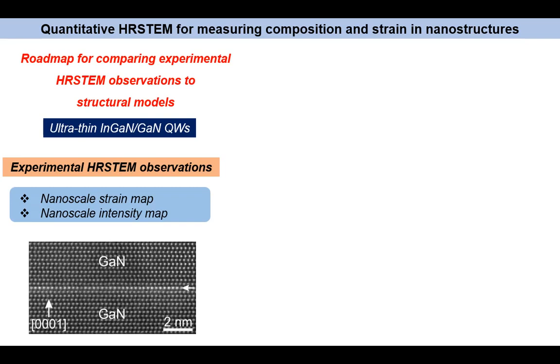So now let me go into more detail on the subject that we are dealing with today, which is quantitative high-resolution STEM for measuring composition and strain. We have developed a roadmap for comparing experimental observations to structural models, and here is an example using these ultra-thin quantum wells of just one monolayer of indium gallium nitride inside gallium nitride. So you get the experimental observations from which you can obtain the nanoscale strain map based on the positions of the projected atomic columns, and also you can obtain the intensity of the atomic columns.